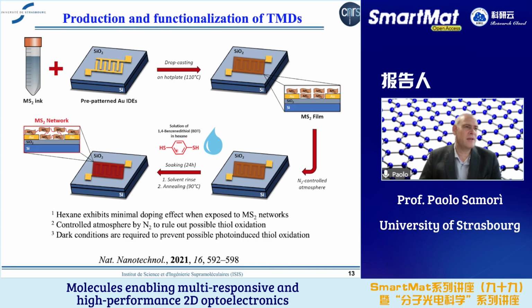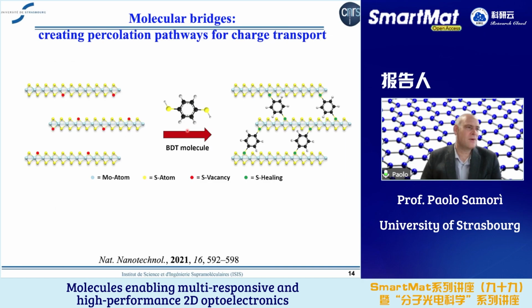Now, what is very important is that this benzene dithiol is dissolved in hexane, because hexane induces a minimal doping effect on MoS2. And then we did this inside the controlled atmosphere of the glovebox to avoid thiol oxidation, and in the dark to avoid the photooxidation of the thiols. And in this way, we produce networks where the flakes are connected like this. And so now let me just prove that this is what really took place. We do a number of characterizations to demonstrate the occurrence.